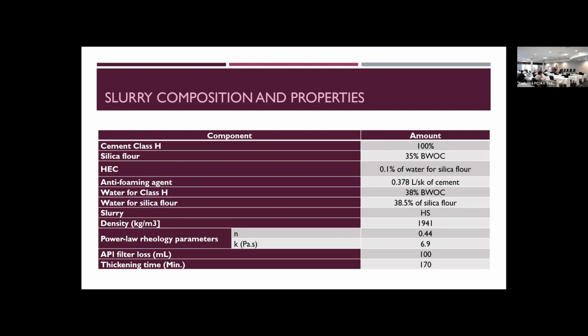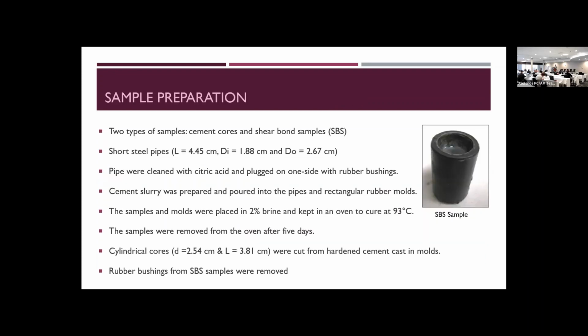For that, we have been using cement class H. We added 35% by weight of cement of silica flour, and then a lot of other chemicals, where we are trying to replicate a given recipe that was proposed to be tested. That's why we have the anti-foaming agent and some other additives. I don't really want to go into details on this because I don't think the recipe itself is very important in this case, but the most important will be the results that I will show you here.